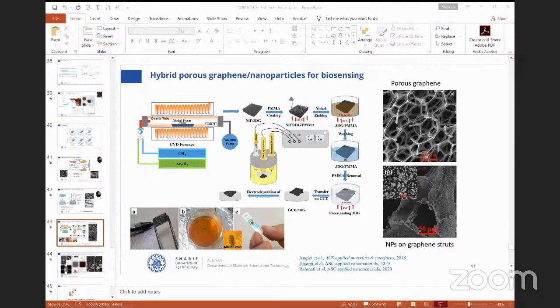As you see here, the SEM picture on the top right shows the structure of three-dimensional graphene. The structure keeps very large pores, creating a lot of surface for biosensing. On the other hand, the ballistic transport of electrons in graphene creates tremendous opportunity for biosensing applications. Then we decorate the surface with electroactive materials, which can be any nanomaterials, gold or anything, and made, as you see in the chip below, a freestanding electrode that can be used for electrochemical detection of various biomolecules.